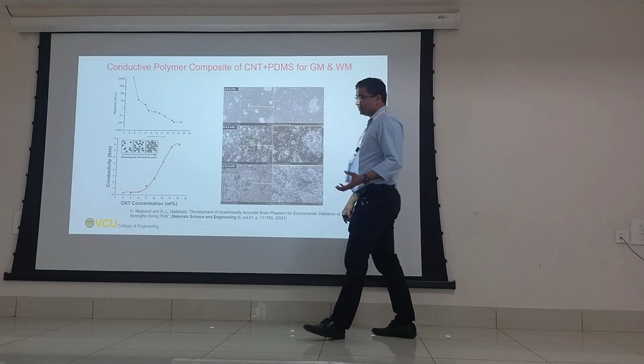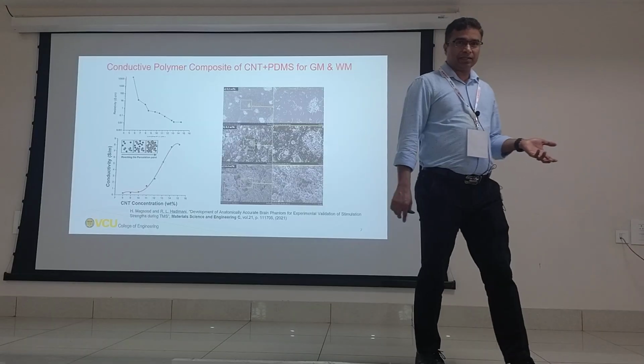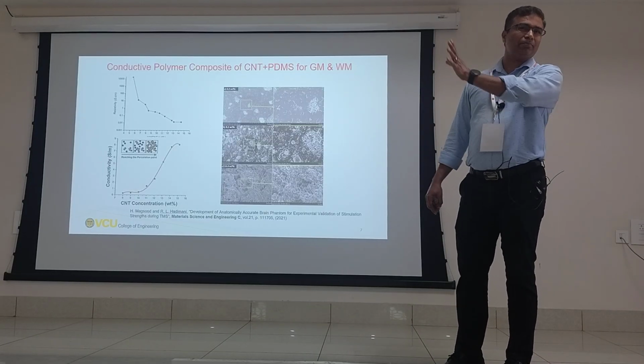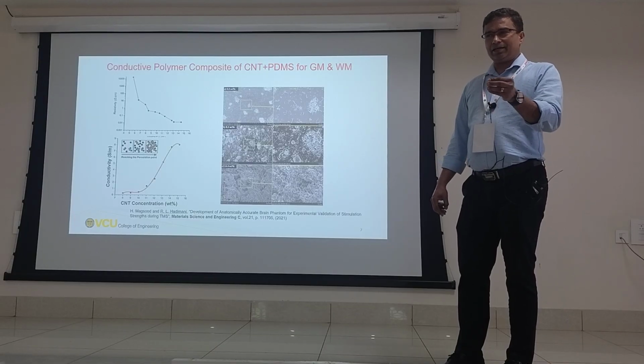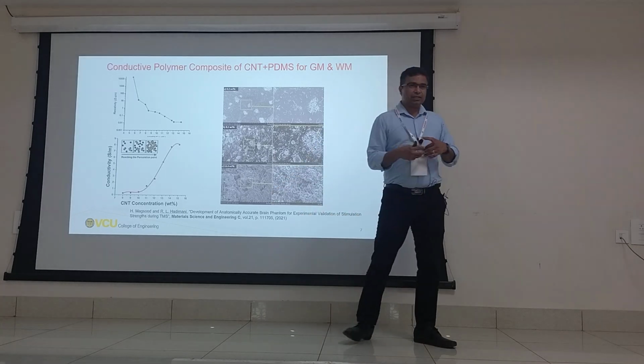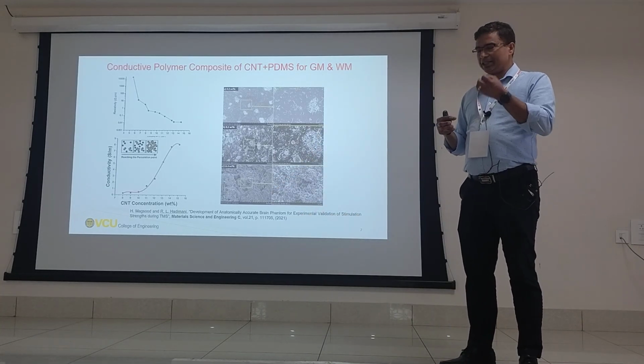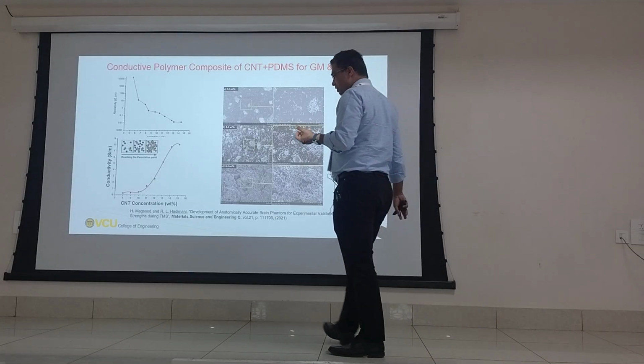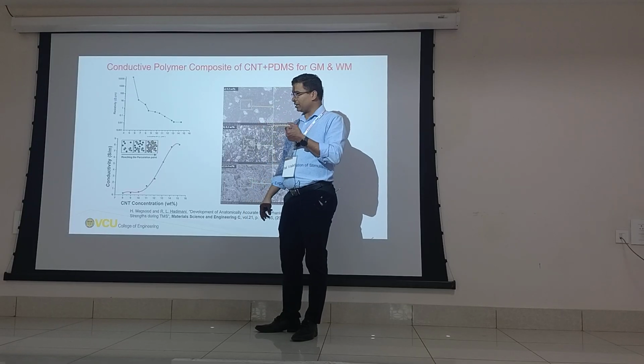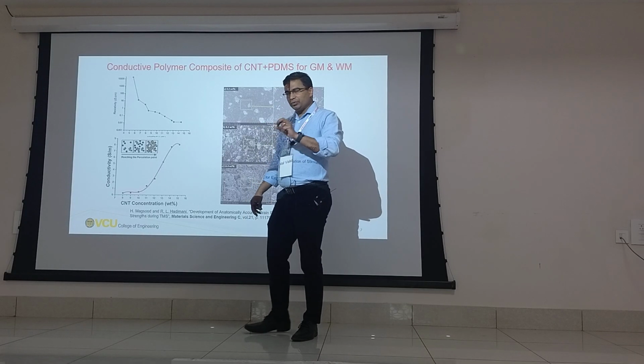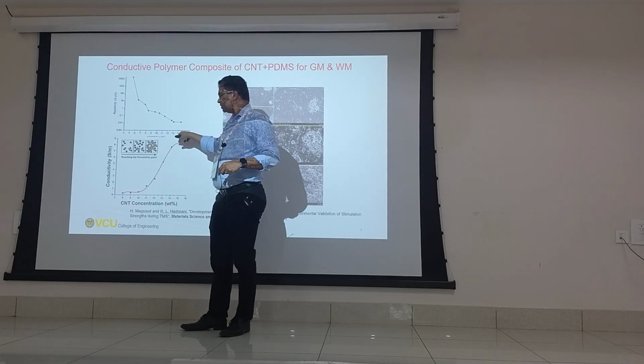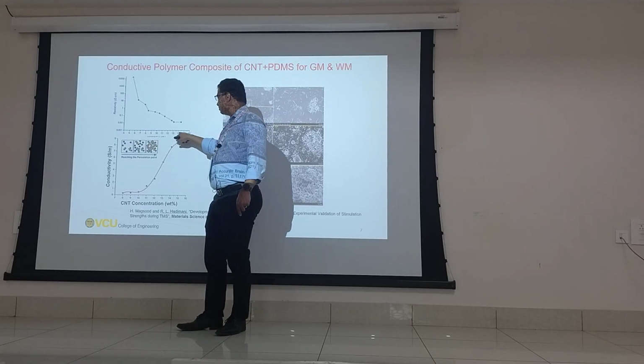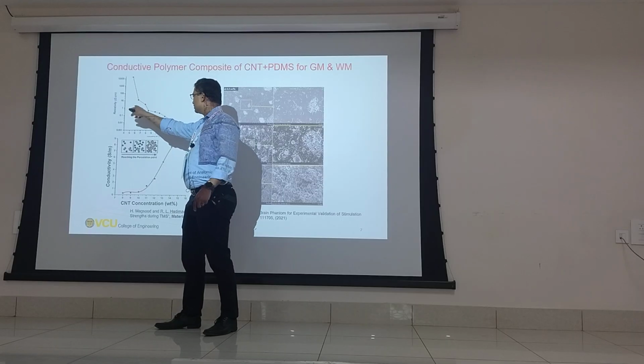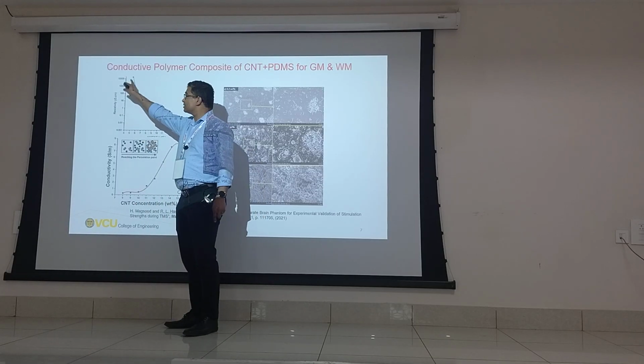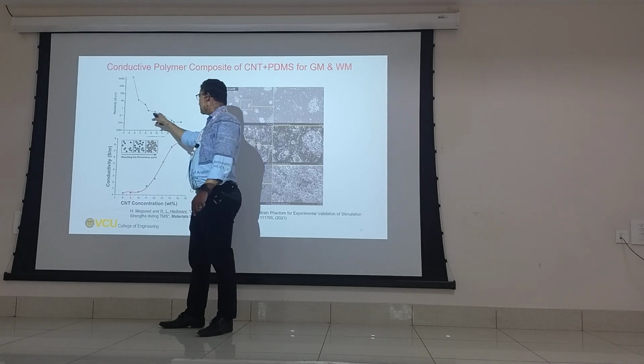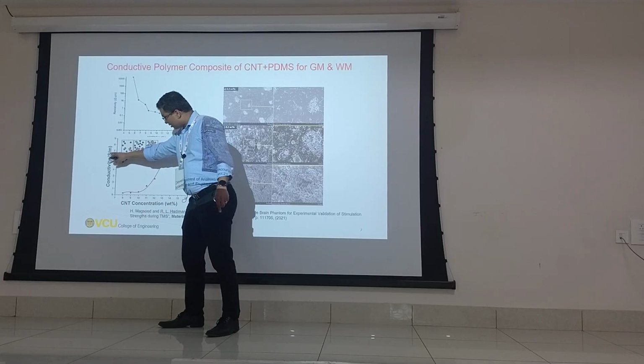So how do you make an electrically conductive polymer? That also did not exist. So we saw somebody trying to make a polymer for some other applications. You take graphene or carbon nanotubes and put them in the PDMS, basically a silicone polymer, and the more carbon nanotubes you put, the more conductive the composite becomes. And we titrated it. We started adding, this is the percent of multi-walled carbon nanotubes. As we added more and more carbon nanotubes, the resistivity started to drop, okay, and the electrical conductivity goes up.